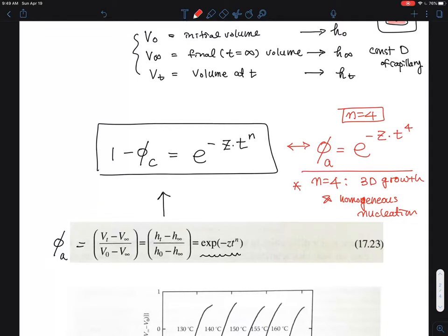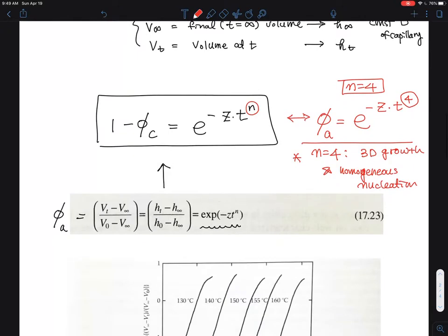Okay, so there was an idea before, and then this exponent 4 was later changed into some different types of crystallization process, and then they get this name. So this is the Avrami equation, and you can get this one based on the DSC or wide-angle X-ray. Actually, this is much more common than the dilatometer.